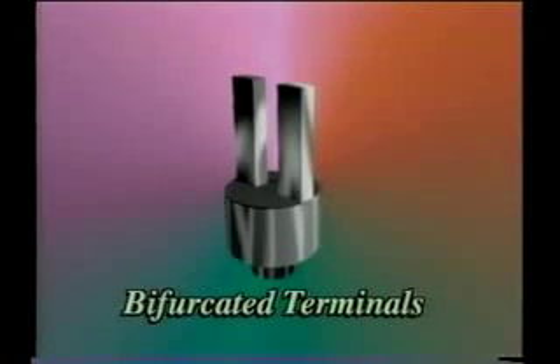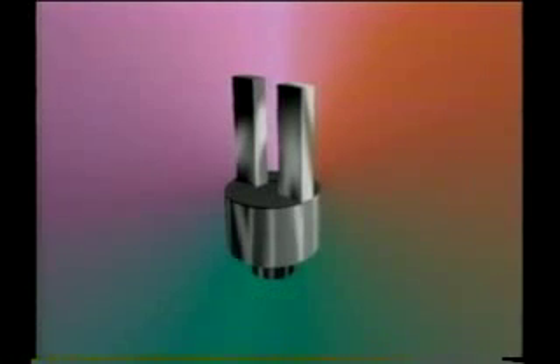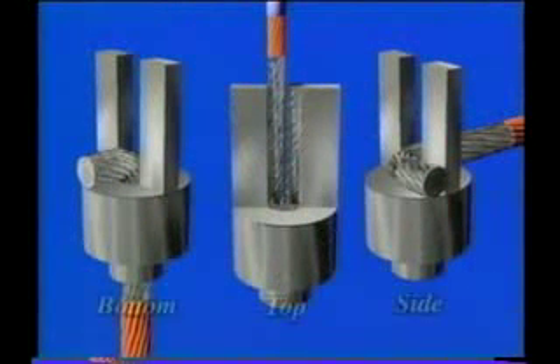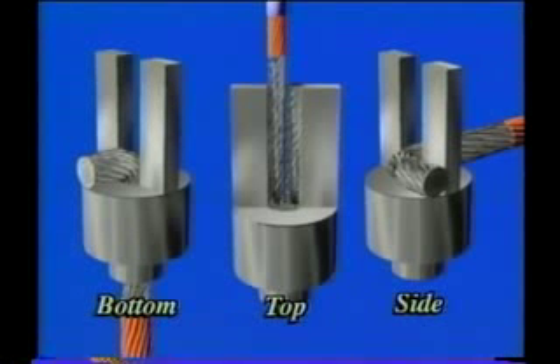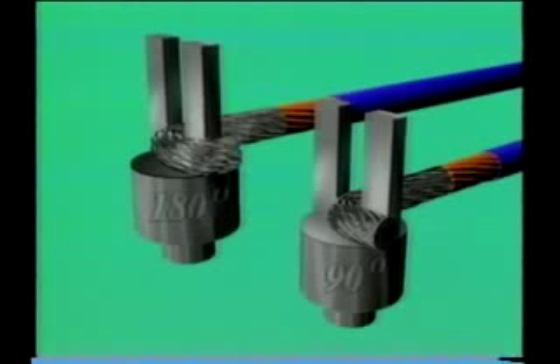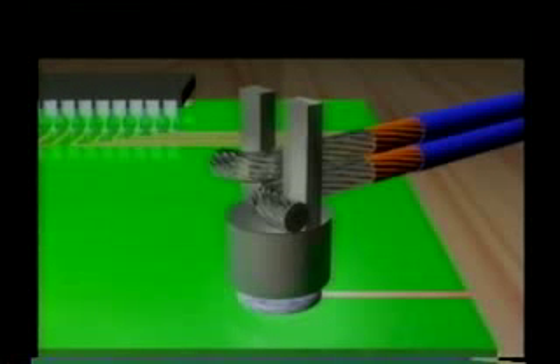Now let's take a look at bifurcated or forked terminals. On these terminals, the wires can enter from the side, the top, or the bottom. Side entry is commonly used when one or more wires are terminated. The wrap you'll be making to attach the wire may be 90 or 180 degrees. 180 degrees is used when additional mechanical strength is desired and when there is sufficient clearance between adjacent terminals. When two wires are required, they should be brought in from the same side and bent in opposite directions.